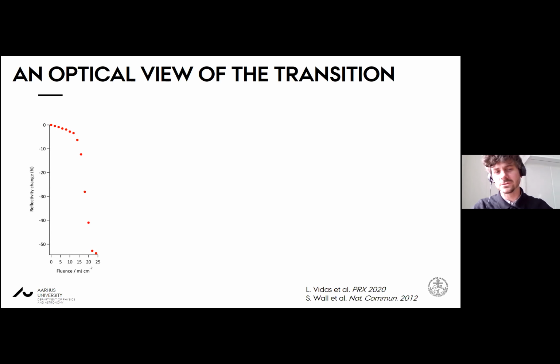Okay, so this is a first order phase transition. And I think as Andrea showed in his talk, when you pump this system, there is a very clear threshold behavior in the change in the reflectivity. So this is the reflectivity change after 1 picosecond. And you see that for low fluences, the change is relatively small. And as soon as you hit the critical threshold fluence, there's a very large drop in the reflectivity, indicating the phase transition. Okay, and then it starts to saturate at higher fluences.